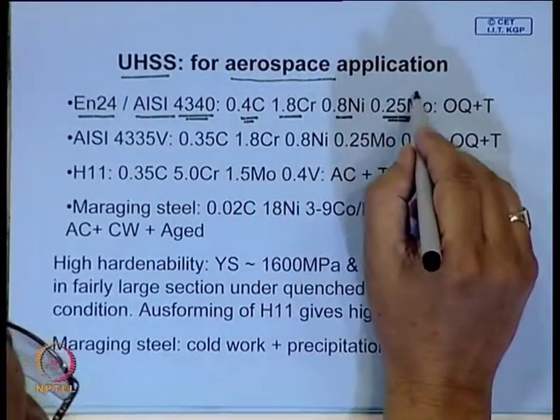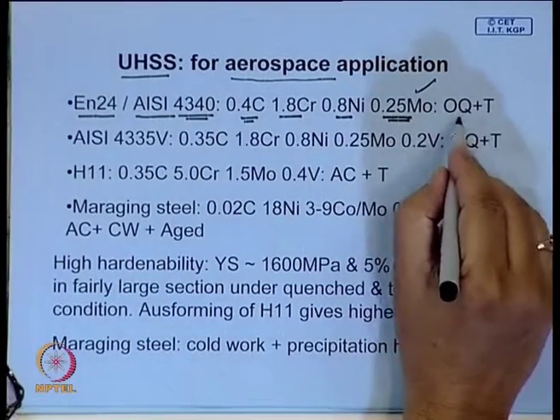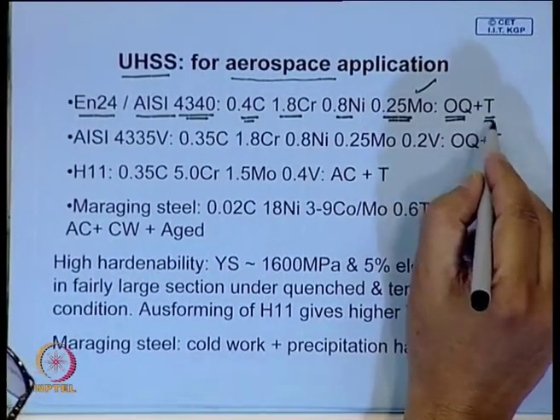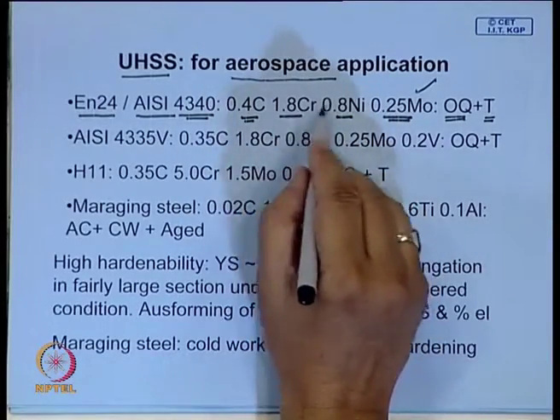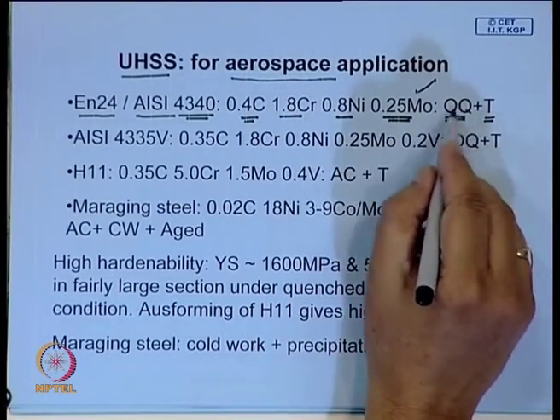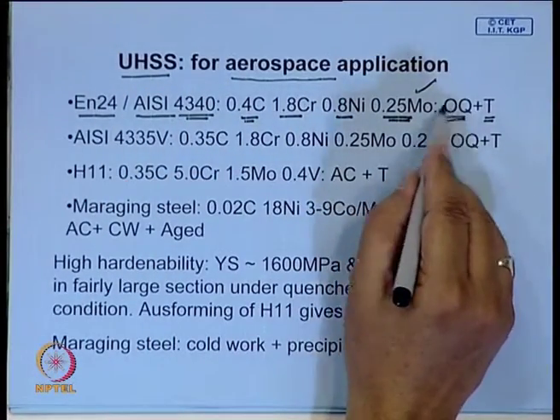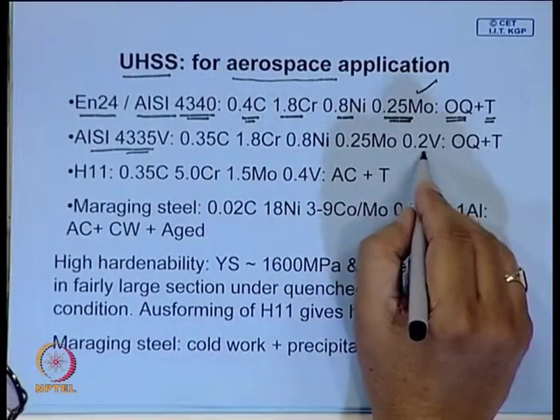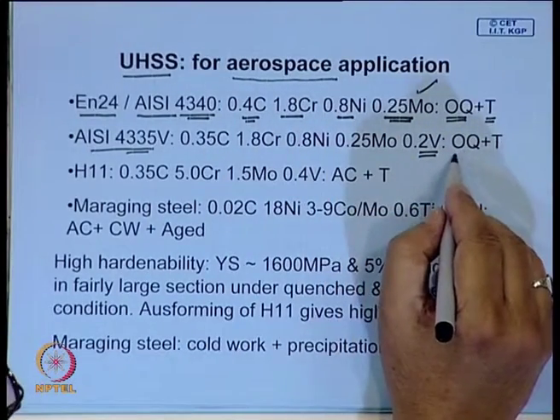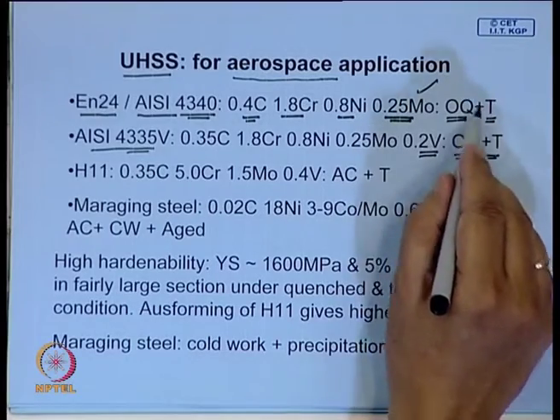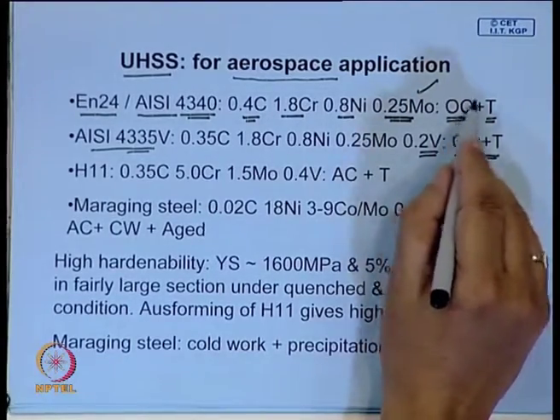When you add these alloy elements, they have a problem of temper brittleness. Addition of moly overcomes that brittleness, and it is used in the oil quenched and tempered condition. Because of these alloy additions, it has good hardenability. By oil quenching, you will be able to harden through and through, particularly for landing gear type applications. This is very useful. There is another grade which is almost based on that. Vanadium addition adds to the strength. Here also the treatment is similar: oil quench and temper. Oil quench from the austenitic temperature range, and obviously we will look for fine austenite grain. You do not heat it to too high an austenitizing temperature.